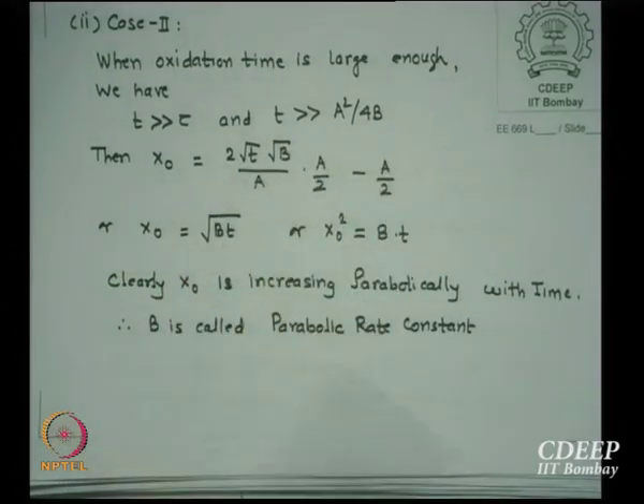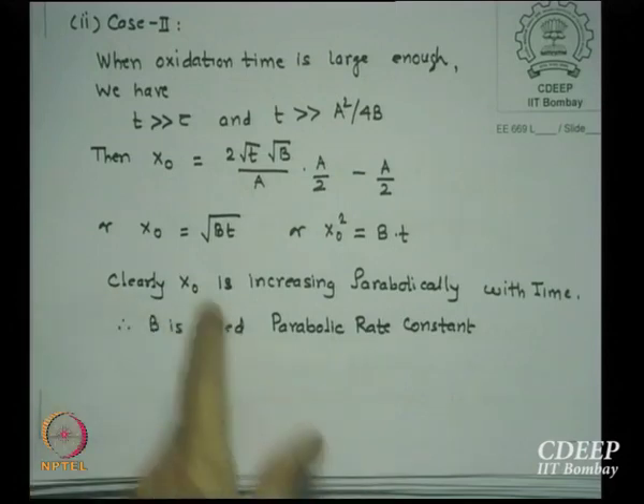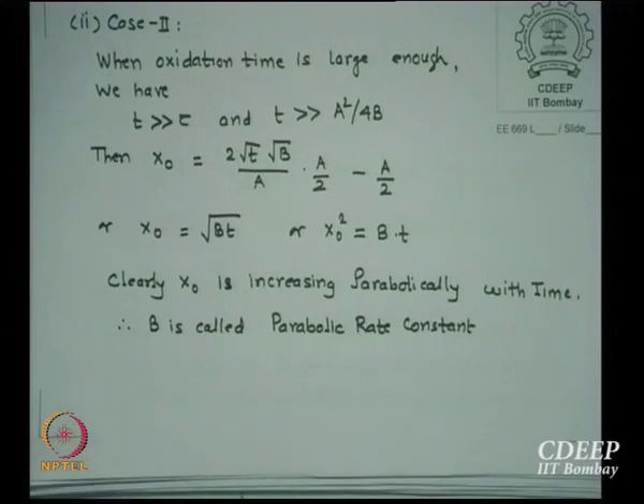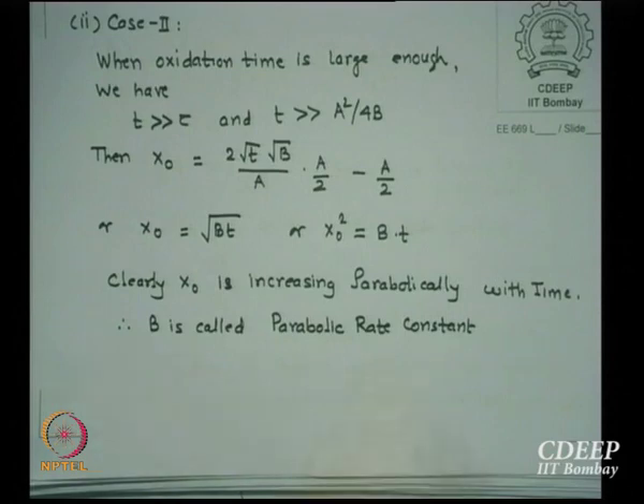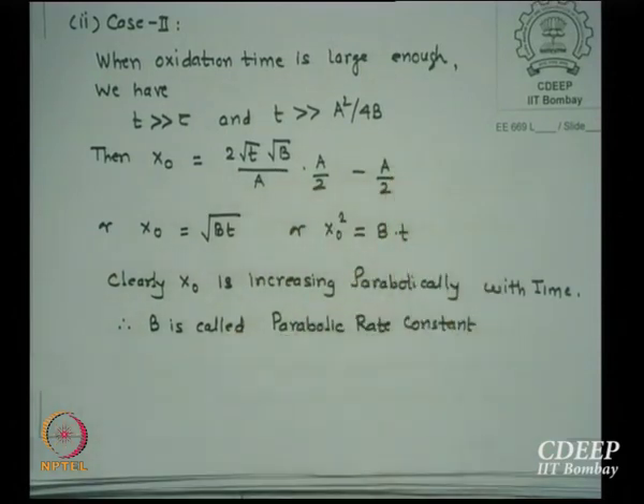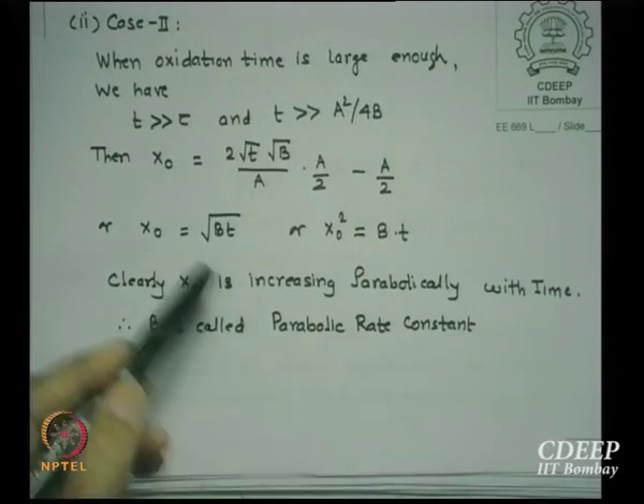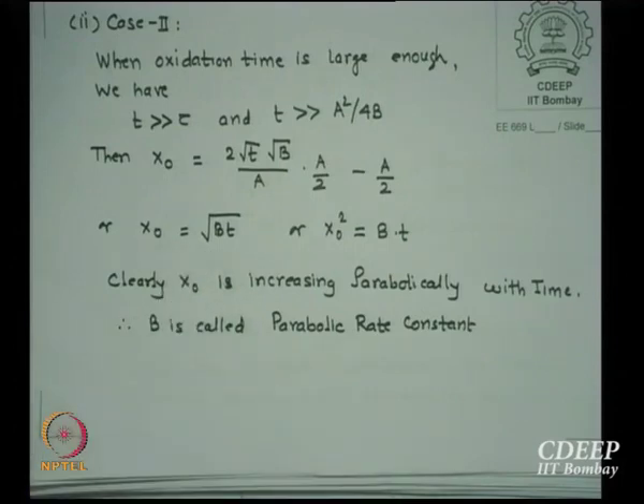2 root tB by A into A by 2 minus A by 2. If I readjust these terms, this is just substituting into the equation which we wrote earlier in the quadratic solution. Substitute t much greater than this, 1 can be neglected there. Therefore, under root of that is root tB into A by 2 minus A by 2. And if I do this, it essentially comes to be equal to root Bt.